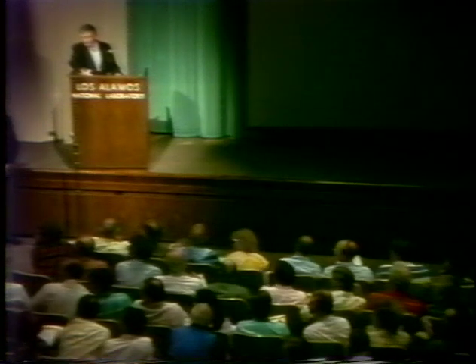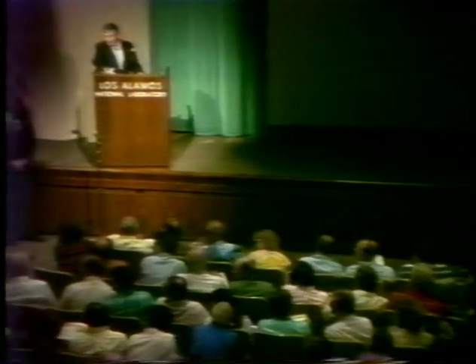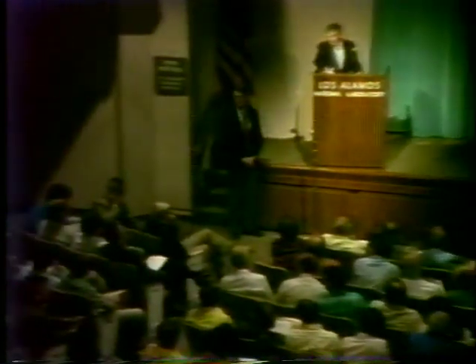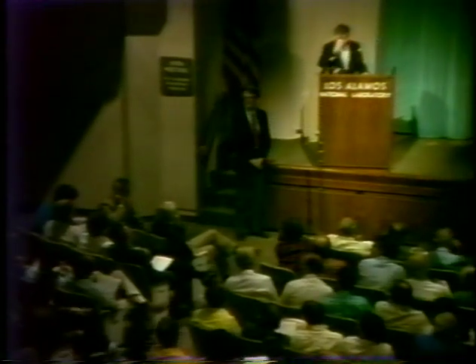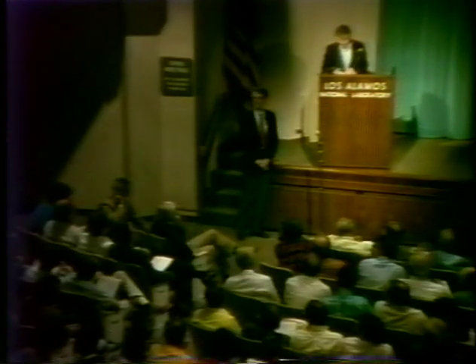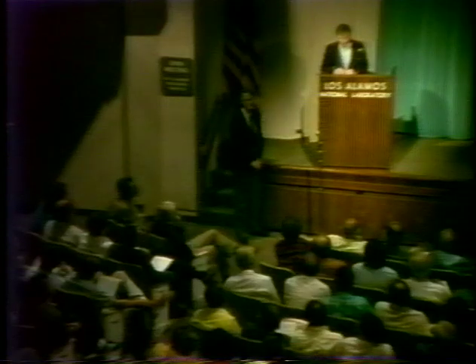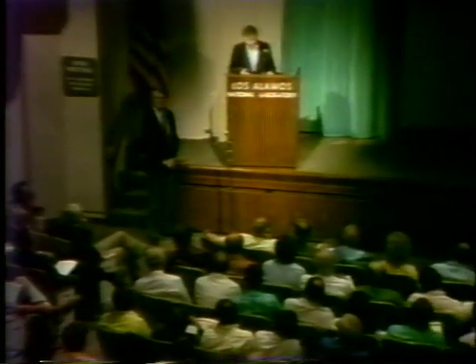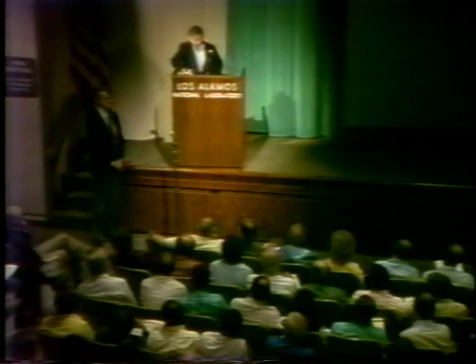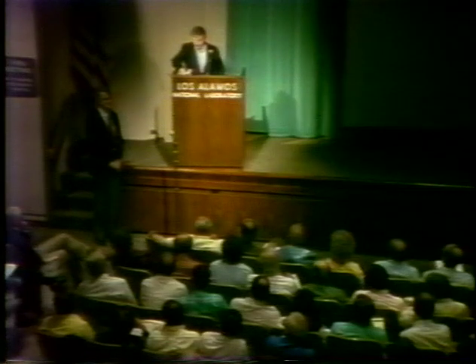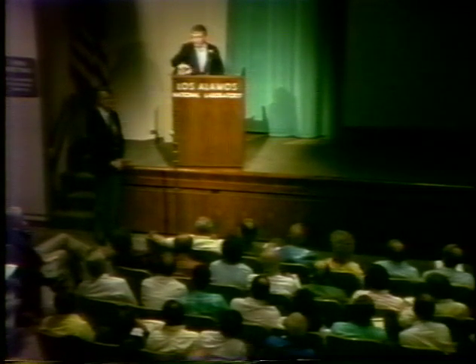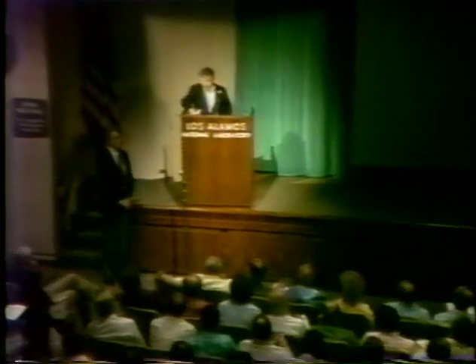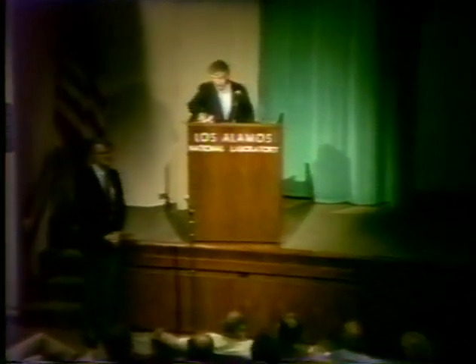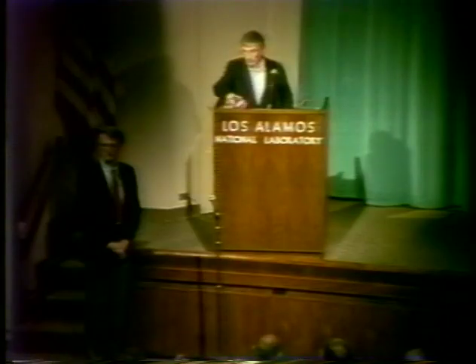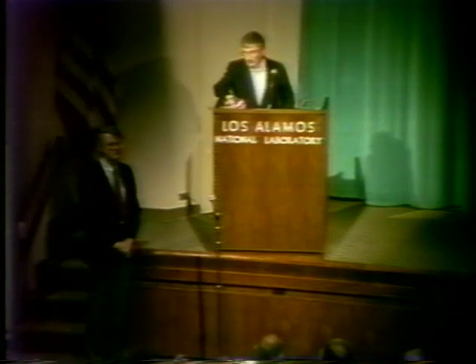Would you just discuss a little bit the ratio of deuterium to the palladium that you are getting in the deuteride, and also the closest approach that you expect that you need to have in order for this to occur? We think from several considerations that we must be close to 1 atom of deuterium per atom of palladium in the metal. In conventional beta palladium hydride, you have between 0.65 and 0.75. That's after you take it out and measure it. But we think under the conditions of the experiment that probably approaches 1. And further, we think that these deuterons are located in the octahedral sites, probably multiple accumulation in the octahedral lattice sites in the metal. Hence the close proximity.